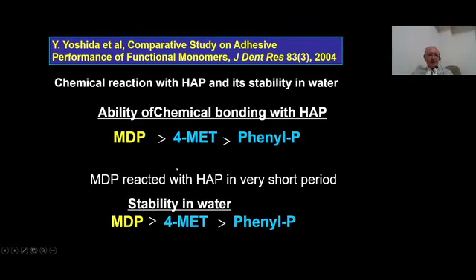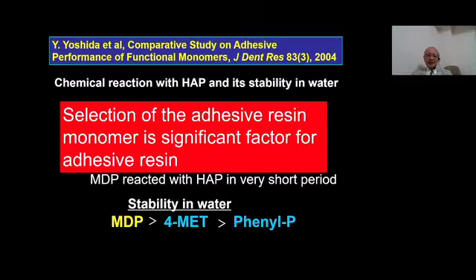After that, the performance of MDP was confirmed by comparing with other kinds of adhesive resin monomers like 4-MET or Phenyl-P. The ability of chemical bonding with hydroxyapatite was the highest with MDP, and also the durability of that bonding in water was the best with MDP. So that's why nowadays many manufacturers use MDP for their adhesive resin material, because the Kuraray Noritake Dental Company kindly released the patent of MDP. Anyhow, the selection of the adhesive resin monomer is a very significant factor for good bonding.